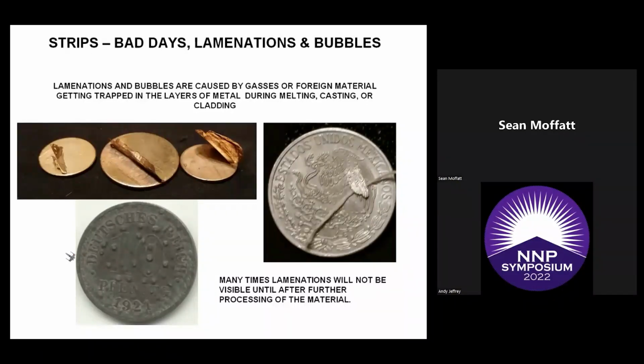As was shown during extruding, when we had bubbles in the strip, those bubbles aren't noticed, and you further process it. The impurities in the metal can cause problems with the metal adhering, and the metal starts peeling apart, as you can see right here in some of these brass blanks that were made. The metal just peels right apart. Wonderful Mexico 50 centavos right here, where the eagle's wing pulled up. I put that string in there just so you can see the separation.